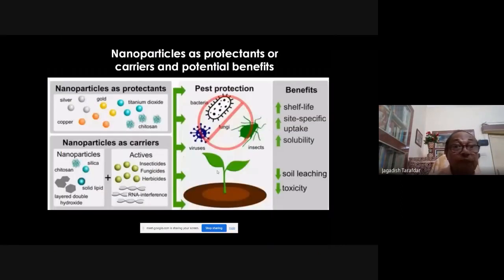So what can nanoparticle do? You can use nanoparticle as protectant against pest, bacteria, fungi, virus. As you can see, it is already proved: silver, copper, gold, titanium dioxide, chitosan. These nanoparticles can protect against pest, bacteria, fungi, actinomycetes. Or you can use nanoparticle as carrier of insecticide, fungicide, herbicide. Silica, chitosan, these nanoparticles are good carriers for insecticides, fungicides. So what benefit can we get ultimately? We can increase the shelf life of your material. Site-specific uptake we can improve. Solubility we can improve. And we can decrease soil leaching and prevent toxicity. So that way also nanoparticle helps.